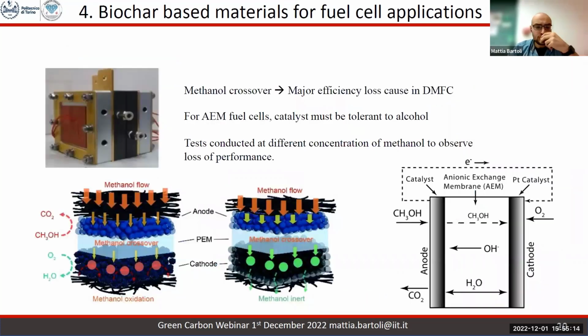So we try to use a methanol direct fuel cell approach that is quite interesting as a secondary energy storage system, in a situation like, for example, when you cannot use an electric generator. And in this case, what you can see from here is that you need a cathode and an anode. And for example, for the cathode, we need platinum-based catalysts. So that was the performances that we must match to say biochar-based material could be an effective replacement.